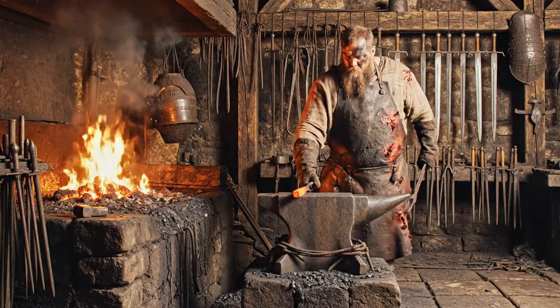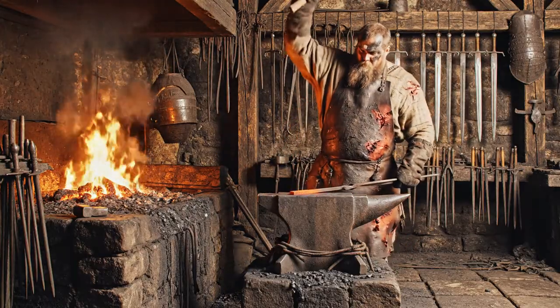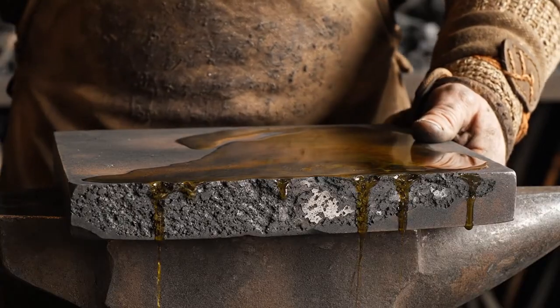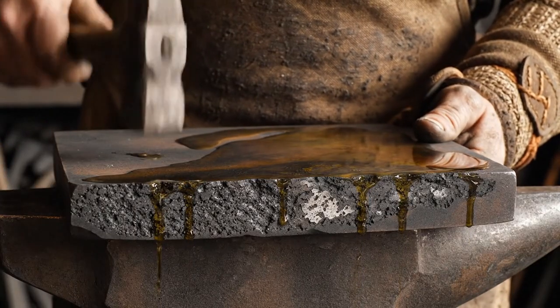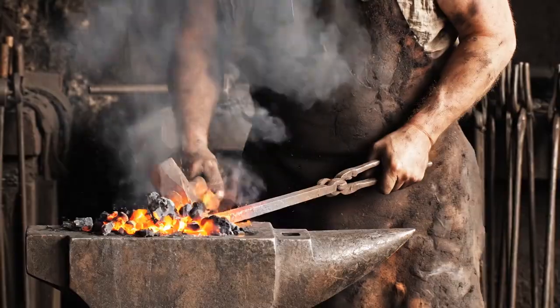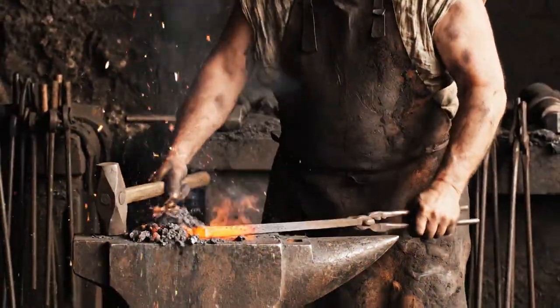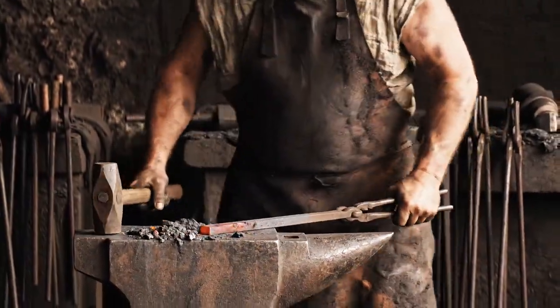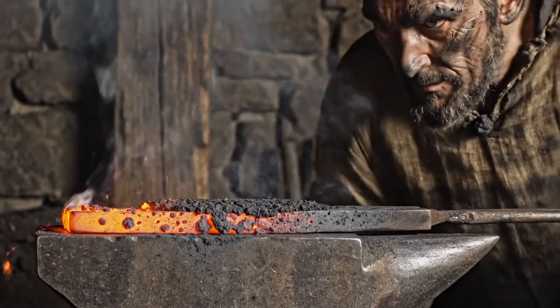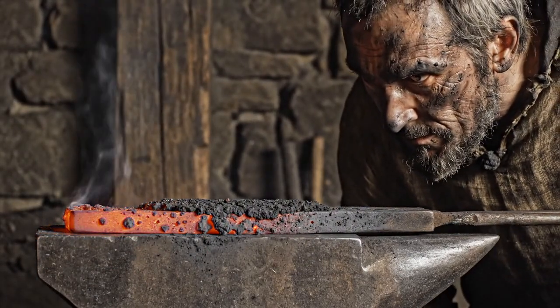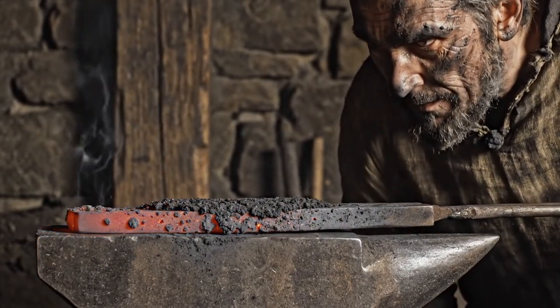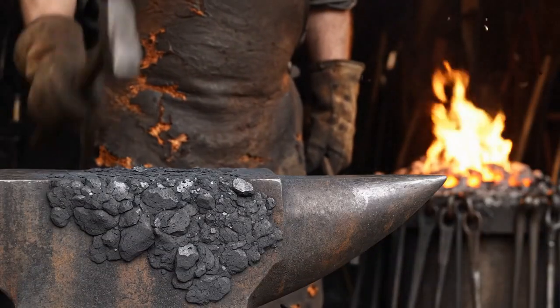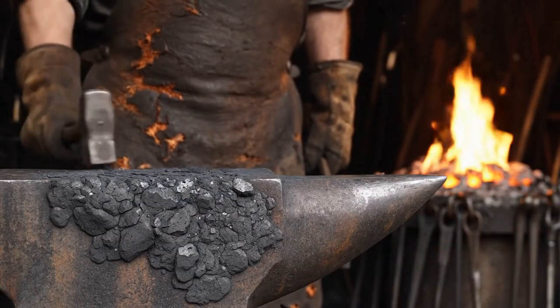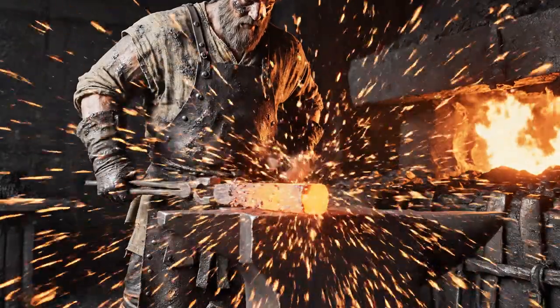Now let us take a step back and observe the complete system that the medieval blacksmith created. Three layers, each addressing a specific vulnerability. The first layer is magnetite. The heat of the forge converts the outer surface of the iron into a dense and stable oxide that acts as a chemical barrier between the metal and the environment. This layer is not applied externally. It grows from the iron itself. It is bonded at an atomic level.